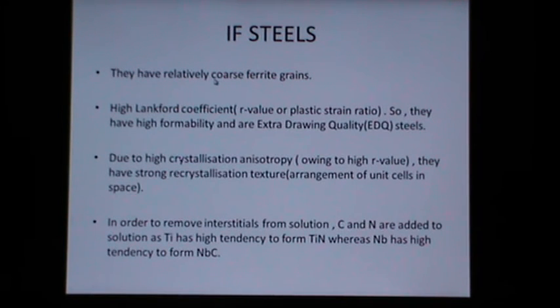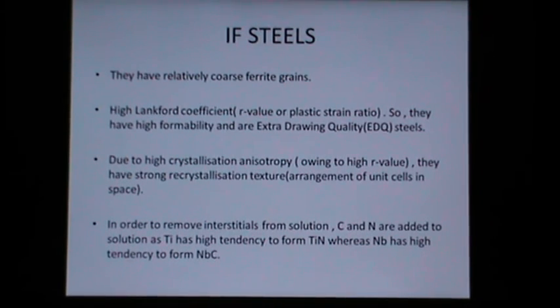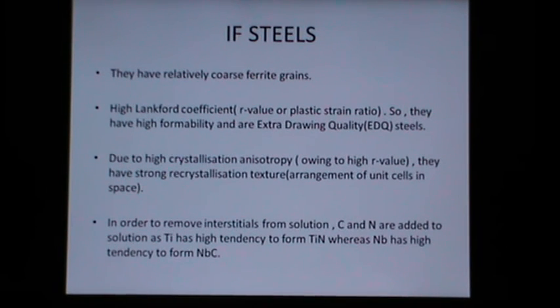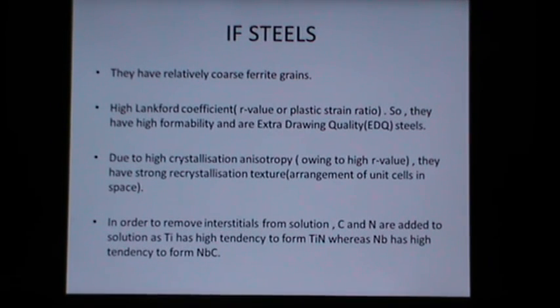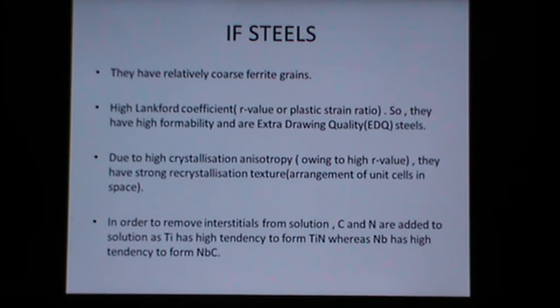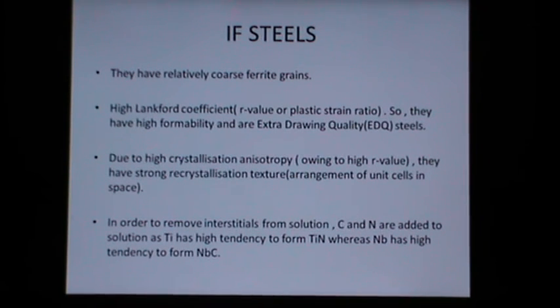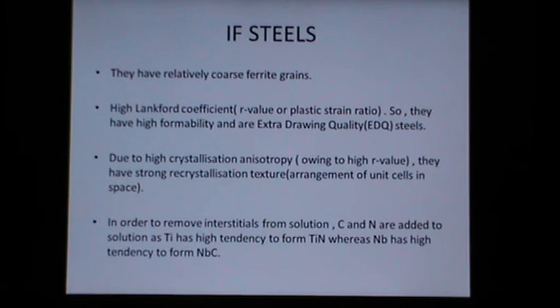IF steels have relatively coarse ferrite grains. Following the Hall-Petch behaviour, we cannot expect high yield strength from IF steels, as yield strength (σ_ys) is inversely proportional to d^(1/2), where d is the grain diameter. IF steels possess a high Lankford coefficient, which refers to a high R-value or high plastic strain ratio, giving them high formability — hence they are classified as extra drawing quality (EDQ) steels.